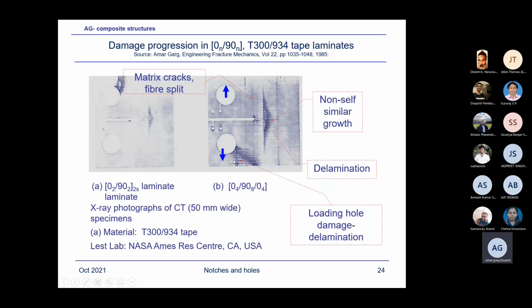Another one, this should be 0, 90. Now, this is a bad layup. In practice, you would never use it. It's terrible because it will lead to delamination. As you can see here, in the loading hole, near the loading hole only, the plies have delaminated.